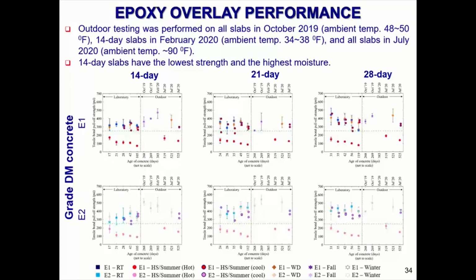And all of the slabs, irrespective of how old the concrete was when the overlay was applied, passed the pull-off test. However, all of the pull-off tests in July of 2020, when the outside temperature was 90, failed. Those were less than 250 PSI.